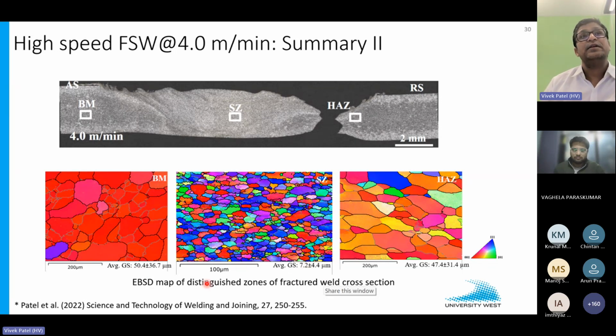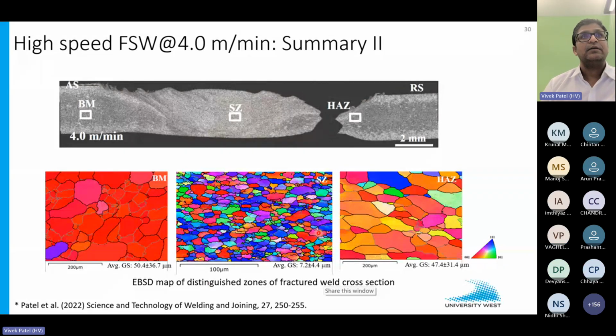And we also found that in a failed specimen after tensile testing, the grains of the stir zone showed some ductility. You can see elongations in the weld nugget itself when the plastic deformation is happening. So far we have pushed the limit up to 6 meters per minute, but so far we got the right properties at 4 meters per minute.